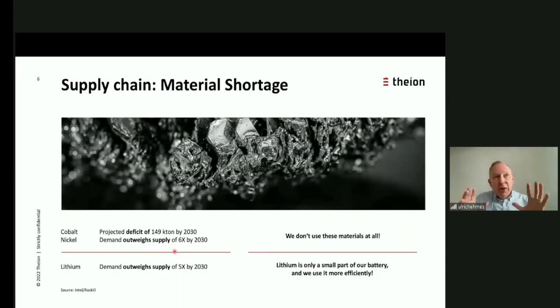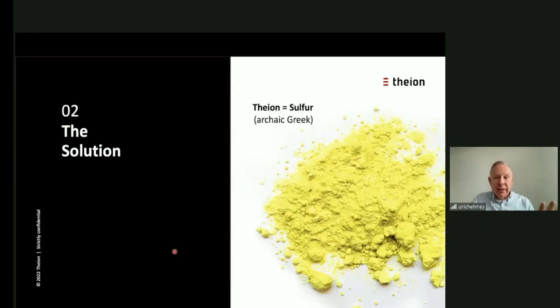The very, very complicated thing for the gigafactories which are planned right now is the availability of raw materials, because there's 6 times more demand for materials than there is availability. But we don't use this material. We don't use cobalt or nickel. We use lithium, but we only need 150 grams per kilowatt hour. And the solution for that situation is sulfur.